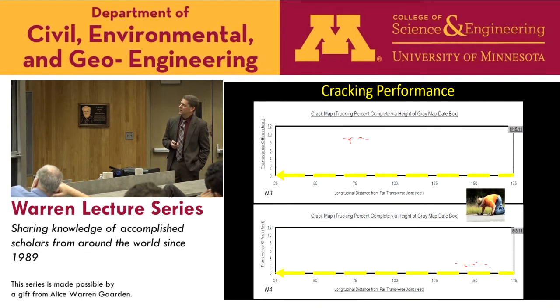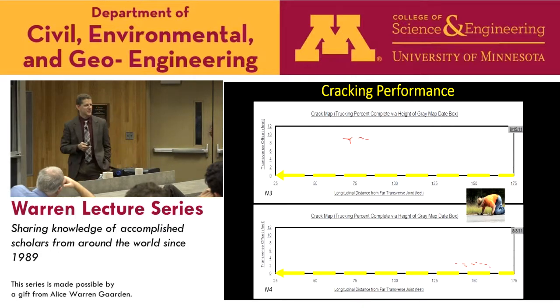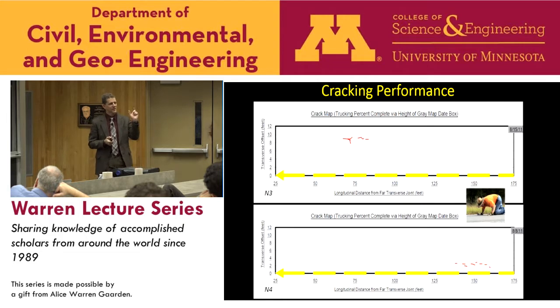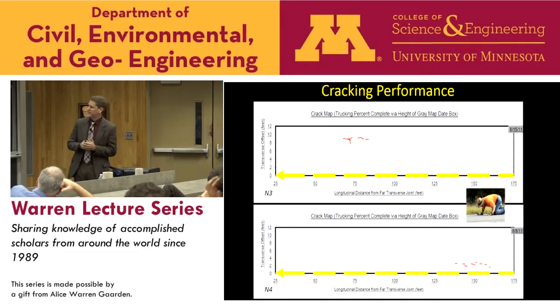We did identify cracks. This is how we detect cracks in the south, by the way. We crawl the pavement. We call it the binocular neural network crack detection system, right? 2 eyes and a brain will detect a crack. And you wouldn't know it, but that pavement surface right now is probably about 140 degrees as he's crawling, so he's wearing knee pads and gloves. But he's able to detect cracks that the high-tech cameras can't catch, and he's able to detect those cracks very early on.